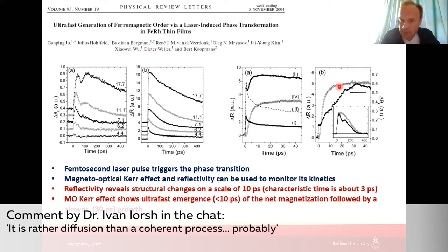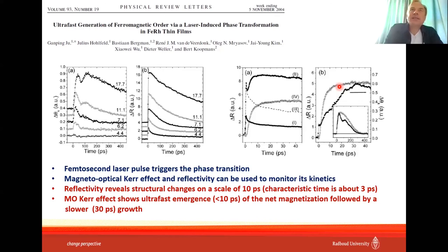Does that answer your question? Yeah, I hope so. So that's kind of a standing acoustic wave, is it? No, it's not a standing acoustic wave. It's not a wave already. So you just put a lot of energy into the system. You launch lattice expansion. So the density of atoms in the medium is less, and if the density reduces, the refraction index will also reduce.